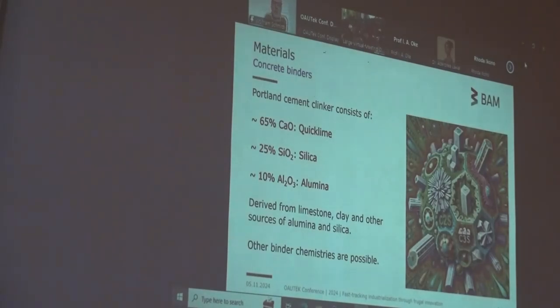So when we have burned our clinker, which finally becomes the reactive material for cement as a binder in concrete, we require about 65% calcium oxide quicklime. We require about 25% silica and less than 10% alumina, which we get from limestone, clay, and other sources of alumina and silica, like bauxite, for example. We use various silica sources. But there are certainly also other binder chemistries possible.